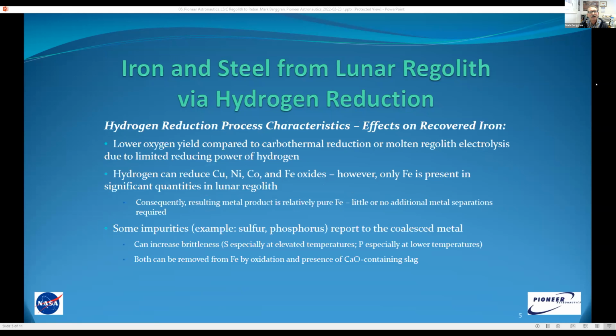So commenting on the hydrogen reduction process itself and the effects on the recovered metal, it's interesting to note that because of the fairly low reducing power of hydrogen compared to carbothermal reduction or electrolysis, that reduces our oxygen yield. But at the same time, because of that reduced reduction power, we can only reduce things like copper, nickel, cobalt, and iron oxides that are present in the lunar regolith. But it's really only iron that's there in significant quantities, the result being that we get a relatively pure iron product directly after separation from the oxide slag.